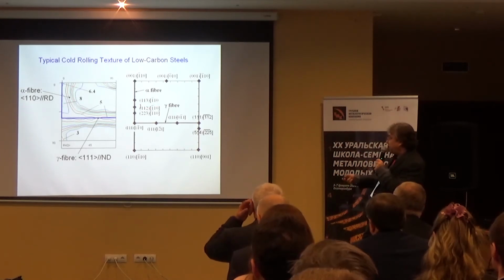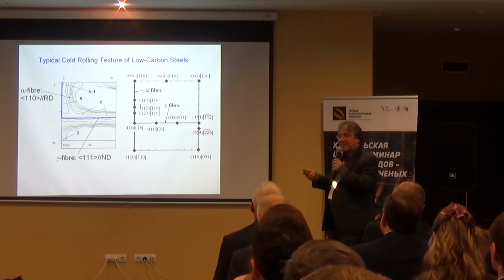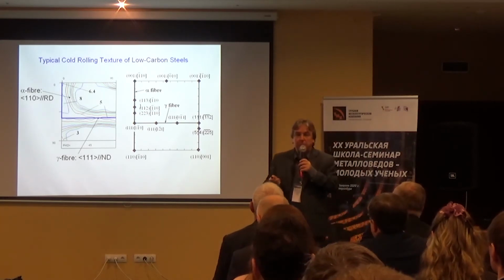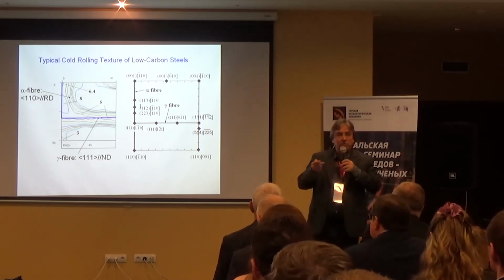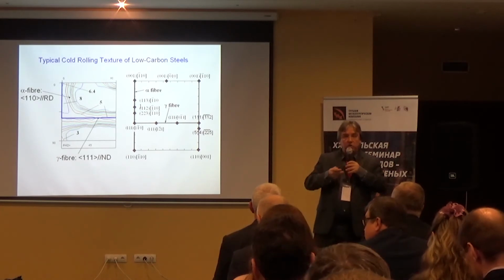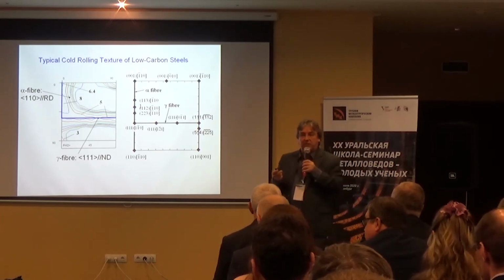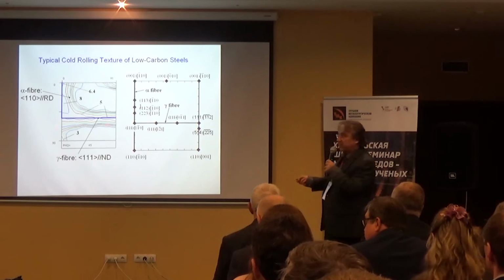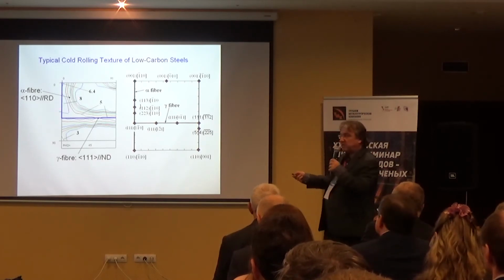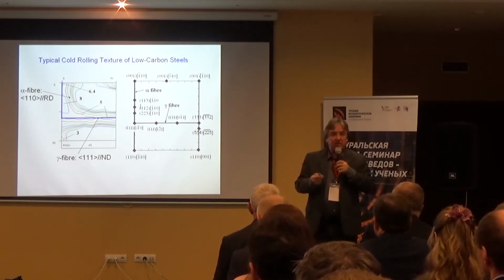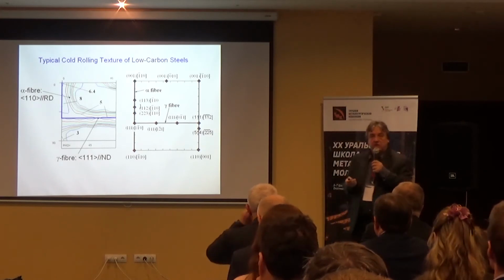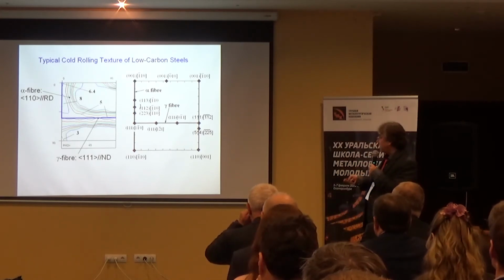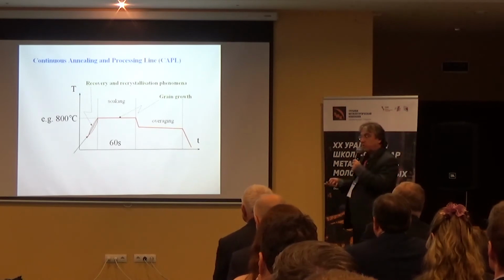And these numbers, 8, 5, 6, these are intensity levels. We compare them with the random texture. So if you would have a powder sample, for example, then all the levels would be equal to 1. So here 8 means 8 times more intense than in a powder texture sample or in a textureless sample. So this was for cold rolling.